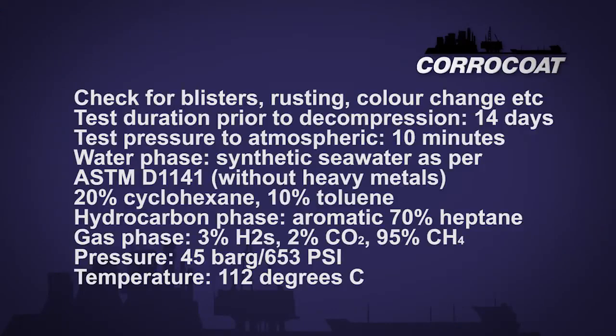Changing the test environment is surprisingly common for testing within the oil industry, often due to the difficulty in obtaining and shipping even small samples of crude oil. For best results, it is always good practice to test the actual oil in question. Let us look at this test regime. The client insisted on testing using a blend of hydrocarbons, including a low molecular weight aromatic substituted for the oil. The coating was tested in an autoclave for explosive decompression and failed. Whilst it was true that a fraction of a percent of the low molecular weight aromatic would have been present within the oil,